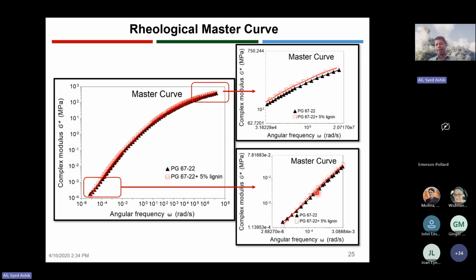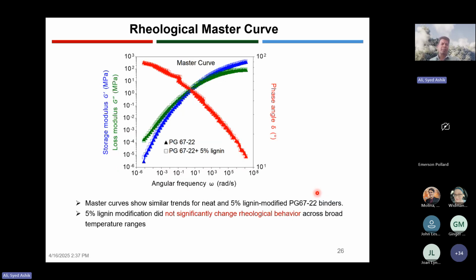So we can expect that, and also we have seen the same thing for storage modulus, loss modulus, and also for phase angle as well. So the master curve is actually showing that the 5% lignin modification did not significantly change the rheological behavior across a broad temperature range or broad frequency.